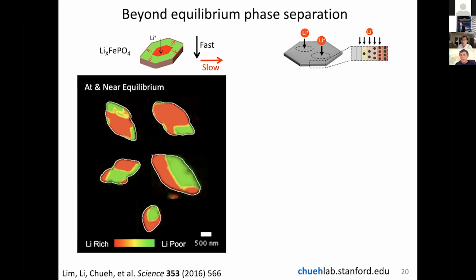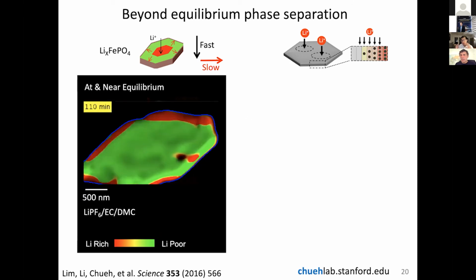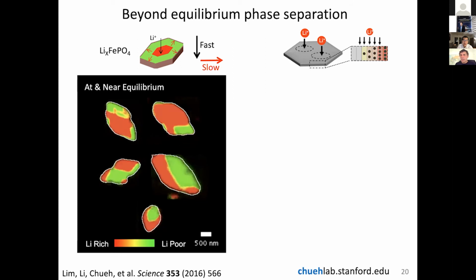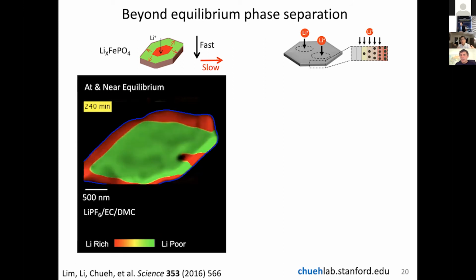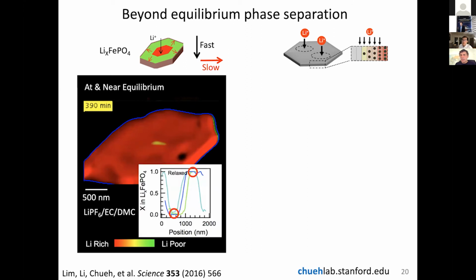This is exactly what you would expect from thermodynamics. You have classical phase separation. If you do this experiment in situ, so now we're watching the phase separation, you see exactly the same thing. You see a phase boundary moving, and in a sort of shrinking core effect, you see the phase propagating, changing from red to green, from lithium-rich to lithium-poor. If you carefully analyze the composition of the material, you will see that thermodynamics is obeyed. You see either red or lithium-rich, or green or lithium-poor. There's nothing in between. So the miscibility gap is never occupied, which is what you expect from thermodynamics.